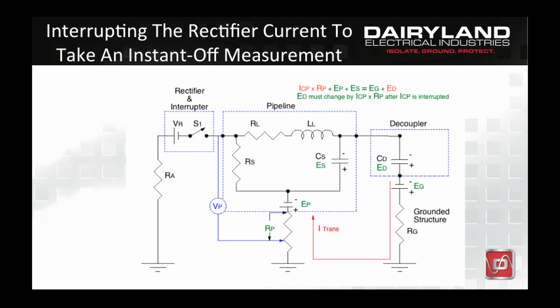However, the voltage across the decoupler must still change by the same value of the IR voltage drop component that was eliminated by turning off the rectifier current, and it takes the same amount of time independent of the grounding conductor material used. In some cases, the decoupler capacitor may need to be discharged and in other cases charged to effect this voltage change across the decoupler. In the above schematic, I show the case where the capacitor is being discharged to effect the required voltage change. An understanding of this slide is key to understanding why an off potential measurement error can exist on some decoupled pipelines.